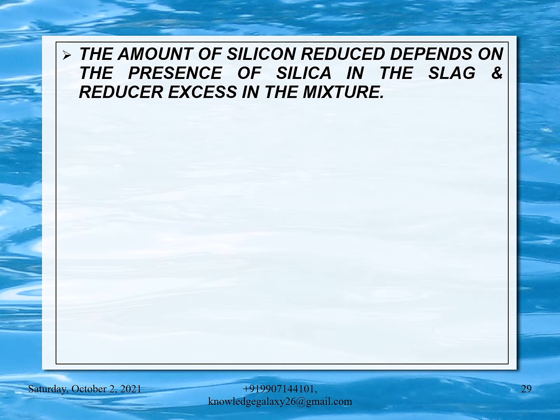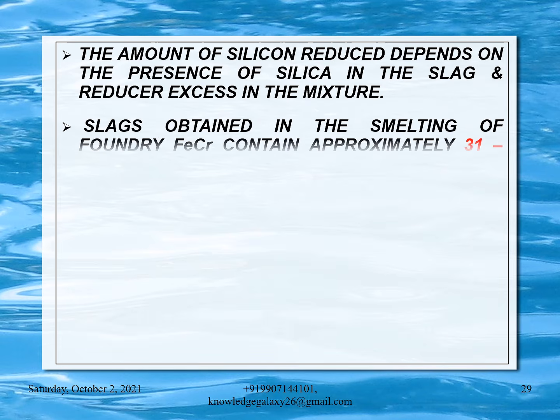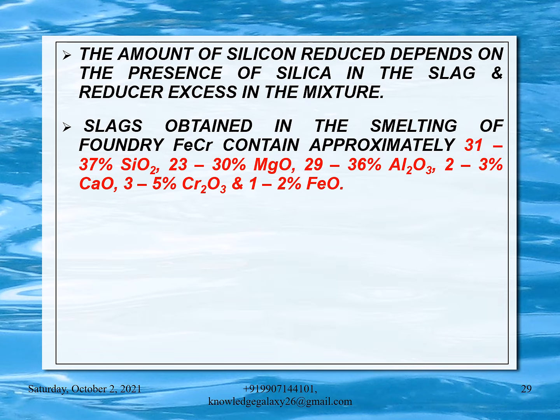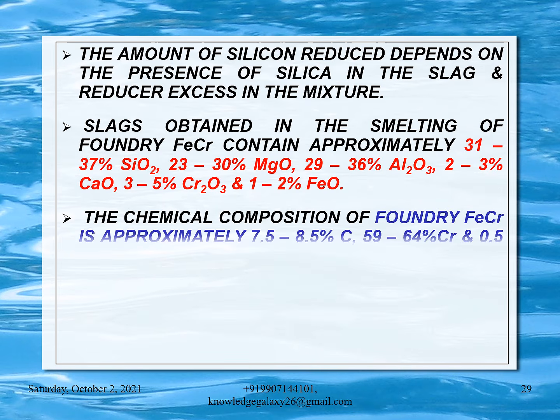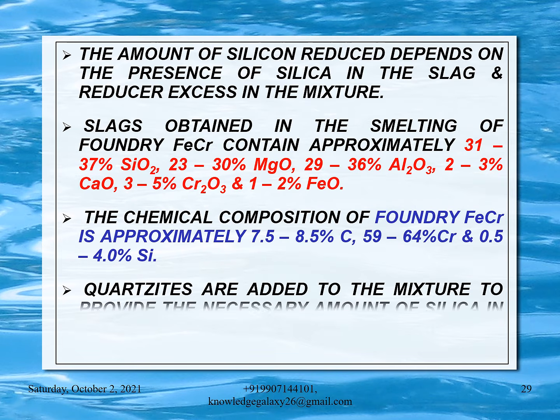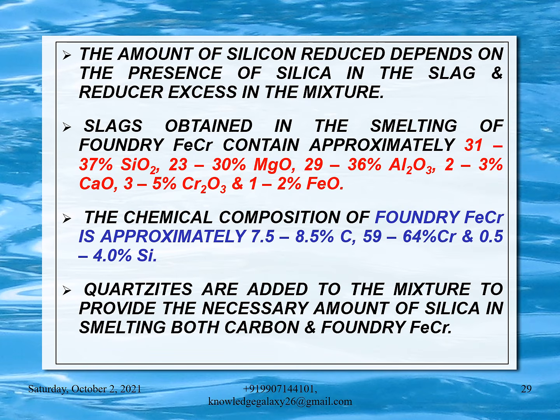The amount of silicon reduced depends on the presence of silica in the slag and reducer excess in the mixture. Slags obtained in the smelting of foundry ferrochrome contain approximately 31 to 37% SiO2, 23 to 30% MgO, 29 to 36% Al2O3, 2 to 3% CaO, 3 to 5% Cr2O3, and 1 to 2% FeO. The chemical composition of foundry ferrochrome is approximately 7.5 to 8.5% carbon, 59 to 64% chromium, and 0.5 to 4% silicon. Quartzites are added to the mixture to provide the necessary amount of silica in smelting both carbon and foundry ferrochrome.